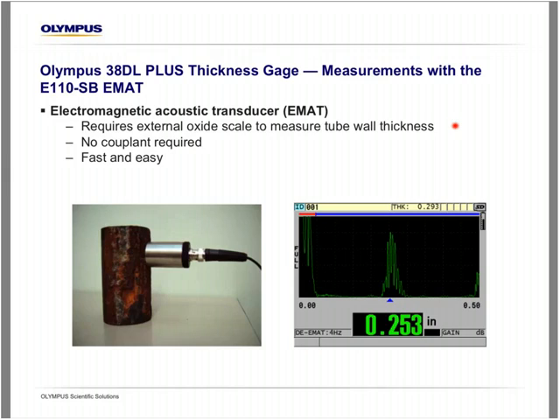So EMAT, or electromagnetic acoustic transducer, is a transducer that generates shear wave sound energy in ferrous metals that are externally coated with high temperature oxide scale. As I mentioned, it's really designed to be a quick way of determining the approximate wall thickness without going through the process of removing the external scale. And the E110-SB EMAT transducer we sell is a very low energy EMAT, so it's not going to work on bare metal. It does require that external magnetite scale to be bonded to the boiler tube. And to be honest, it only really applies to this boiler tube application.